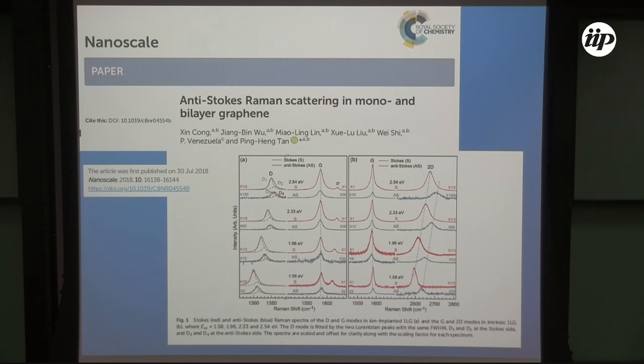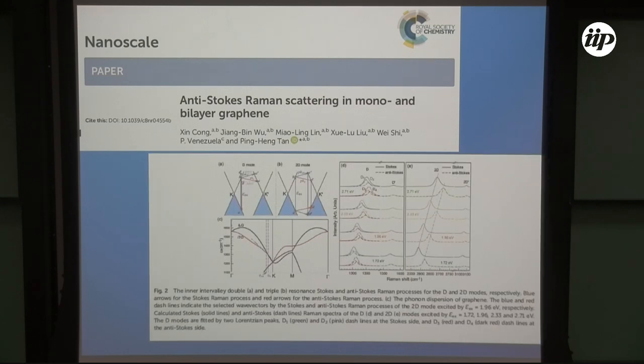Okay, so what we see is that, for instance, here, for the G peak, the Stokes and anti-Stokes peaks are in the same position, but for the 2D peak, they are not. Okay, and the reason is because this is a single process, so in here, it doesn't matter if it's Stokes or anti-Stokes, I am creating or annihilating the same phonon, and here I am creating or annihilating different phonons. And it's easy to understand if you look at this figure here, for instance.